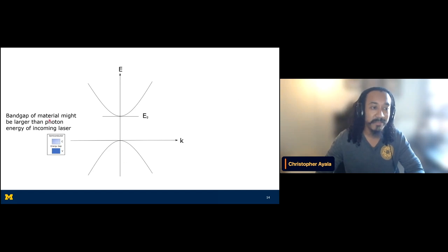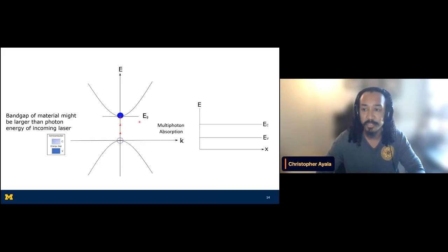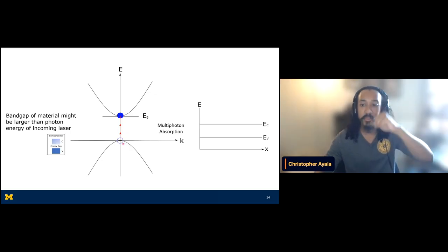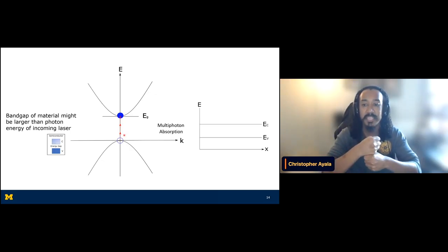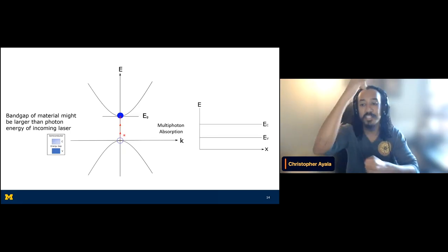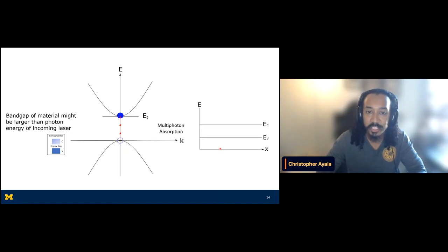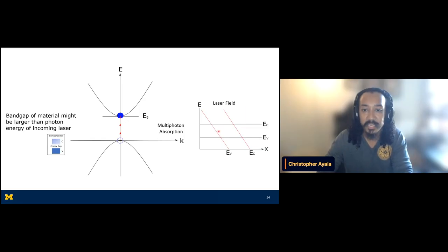In the case where the band gap of the material might be larger than the energy of the incoming photon, you will need something called multi-photon absorption. That just means that if the energy that you have is not enough to bridge the gap, you use multiple photons of the same energy to sum and bridge that energy gap. The right image here is a representation of position versus energy with the valence band and the conduction band. When you turn on a laser field, the valence band and conduction band bend, giving an easier way to model the tunneling that we have seen in the gas phase three-step model.